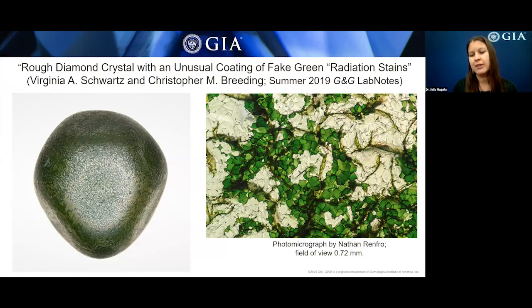This 6.49 carat rough diamond has a patchy green surface color that was caused by interlocking platy crystals of chromium oxide that were visible with high magnification. We suspect that this diamond was meant to mimic most natural green diamonds that are colored by radiation damage. In irradiated diamonds, this process occurs at very shallow depths in the Earth's crust over long periods of time. Commonly accompanying this exposure to radioactive minerals and fluids are surface patches of green or brown color that gemologists call radiation stains. These are simply areas of extreme damage to the diamond structure caused by alpha particle radiation. And that's what we think that the manufacturers were trying to mimic here.